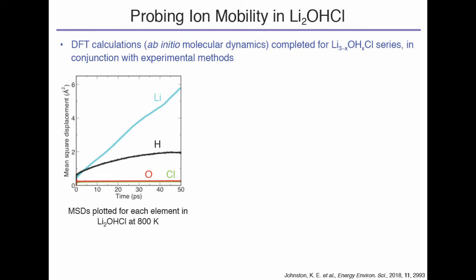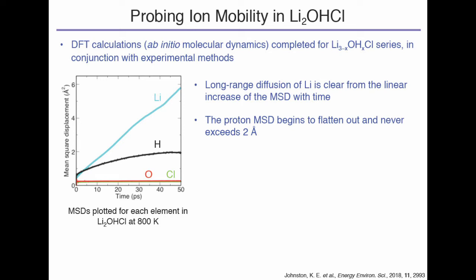Again, because this was working in combination with Seifel and James, they decided to do some ab initio molecular dynamics calculations. Basically, what they wanted to see was, from their calculations, could they see any lithium diffusion? Could they see any proton diffusion? And how does that correlate with our experiments? So they can do mean square displacement plots as a function of time, and all that's doing is trying to see if the lithium is moving, if the proton's moving, if the oxygen is moving, and if the Cl is moving.